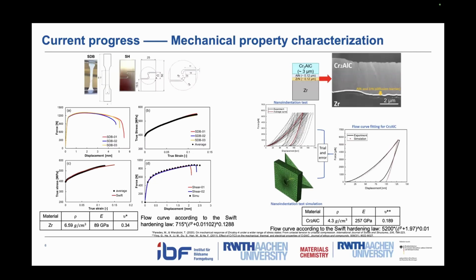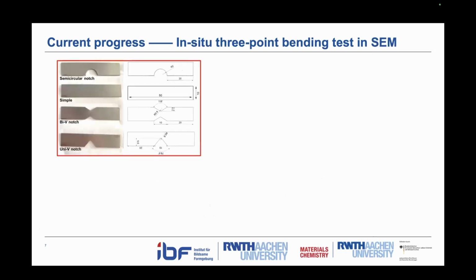I also have to mention that for zirconium, the thickness is 0.7 millimeter, and for the coating, we have finally determined it to be 3 micrometer. The next step is that we manufacture our zirconium sheets into several geometries because we want to cover a wide range of stress states. Then we coated the chromium aluminum carbide onto these manufactured samples.